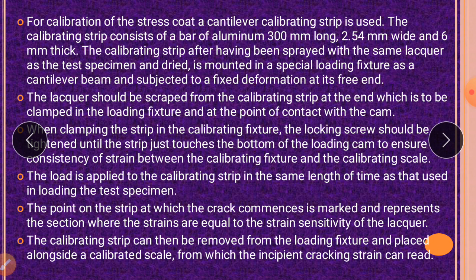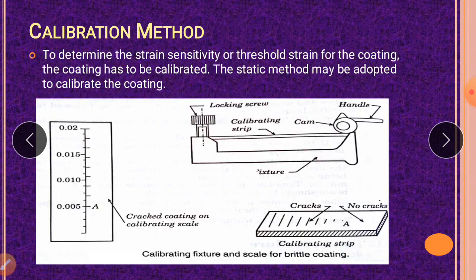Okay, thank you, students. I hope you have understood the method of calibration. You just have to use a special fixture. One end is fixed, one end is free. By using the cam handle, you apply the load. The strip is bent and acts as a cantilever beam. When it is bent, stresses are generated in the aluminum strip and also in the coating. This coated strip is removed and taken for crack determination, where you can see the cracks. The cracks are placed with respect to the calibrating scale, and this scale represents the amount of strain developed at different portions. By that we can calibrate a brittle coating.